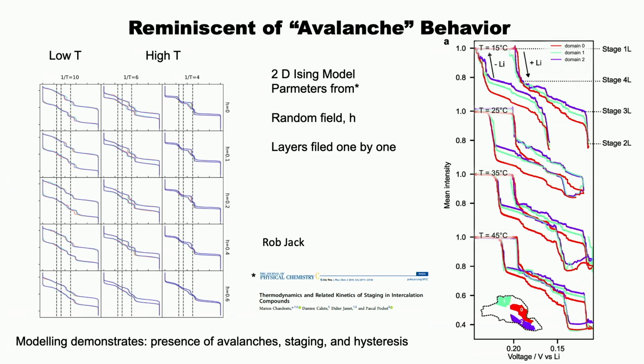And what those little series of steps correspond to is the individual filling of one layer at a time, which we can actually see step by step in these simulations. And so in retrospect, like all experiments, this is obvious, but previously people just thought about this as a solid solution process. And it starts to resolve the questions people have in terms of how you go from alternating 3 layers to 2 layers and to 4 layers, or vice versa. And we can model this, I won't go into great detail, with a very simple Ising model with different degrees of relationships between the layers and also defects within the layers.